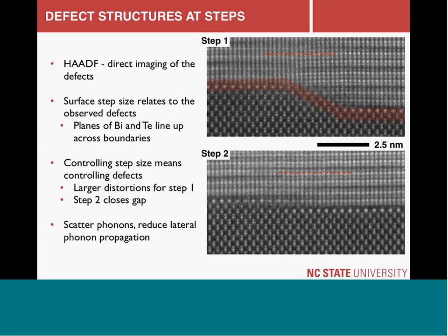Okay. If you follow the layers, these bright layers are bismuth, and the next brightest in between are tellurium. So these, we know that. Okay. So being able to follow a line across the interface, you just have to follow across there.